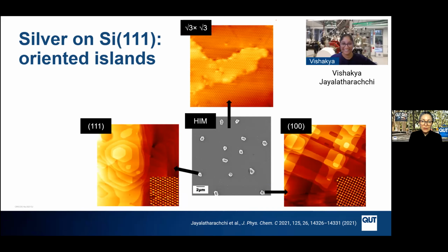And these grew both in a 111 orientation and a 100 orientation. You can see here STM images both of macro scale features of those islands, as well as the atomic resolution. We further confirmed this with X-ray diffraction off of the surfaces. So depending on her growth conditions, she could either grow a predominantly 111 oriented set of islands or 100, or she could have a mixture of both 111 and 100 oriented islands on the same silicon surface.